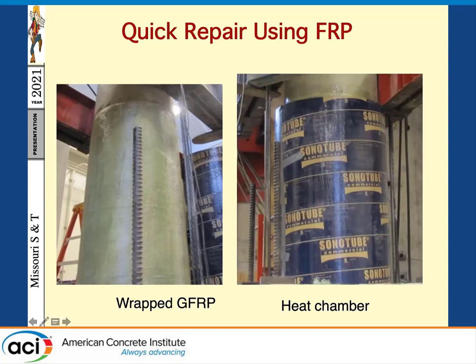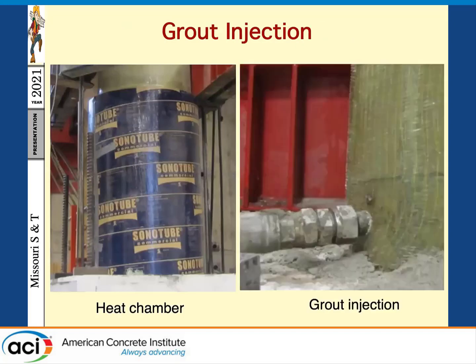We have a lot of thermocouples to ensure that the temperature was constant at 50 degrees. So with those thermocouples, we held the 50 Celsius for about 4 hours. After the 4 hours, this was the selected curing time for the FRP. And then after the 4 hours of thermal curing, we did epoxy injection.